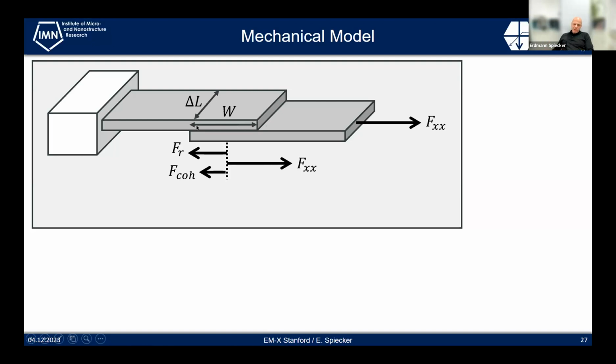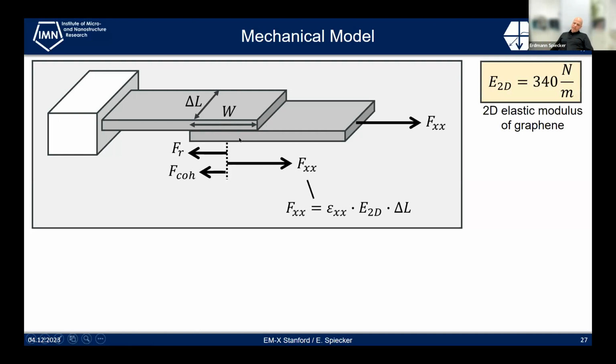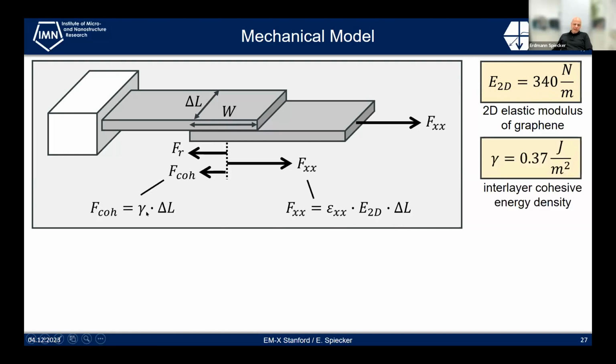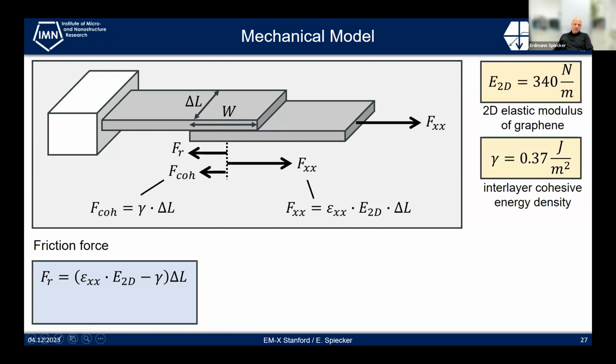Let's assume we have an overlapping width of W, and we consider a stripe of width delta L. Now we can estimate or determine the forces by knowing the 2D elastic modulus of graphene, which is 340 Newton per meter, and the epsilon xx that we measure, we can determine that force per delta L. We can also calculate the cohesive force by the interlayer cohesive energy density times the width, again, delta L. So from that, we can derive the friction force and the difference of these forces.